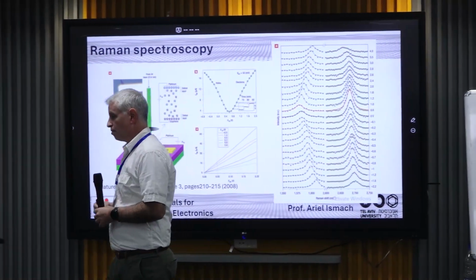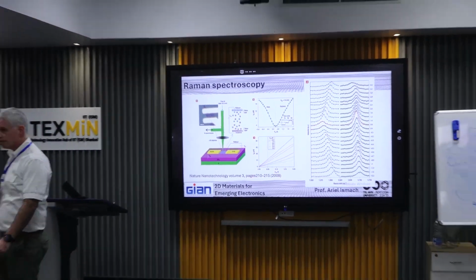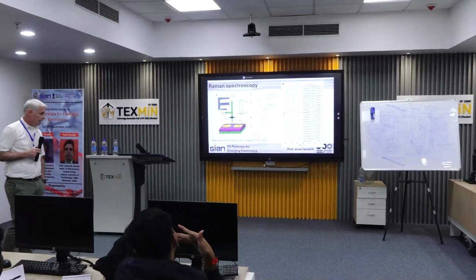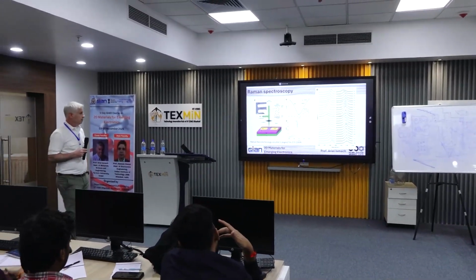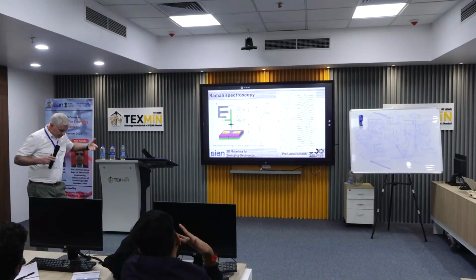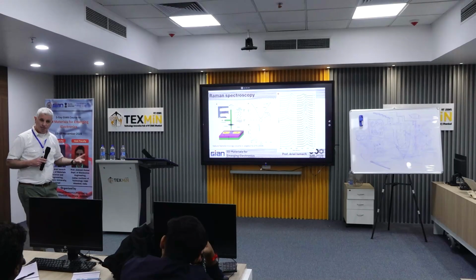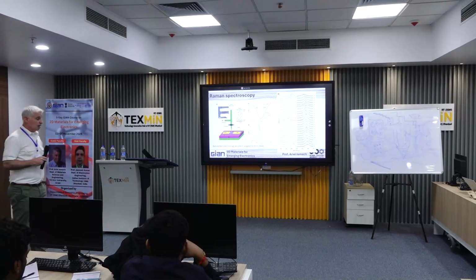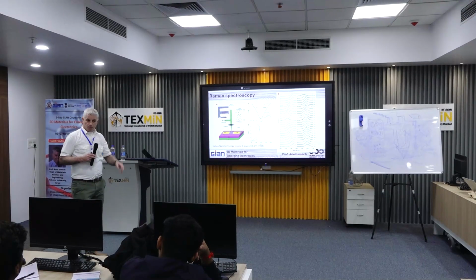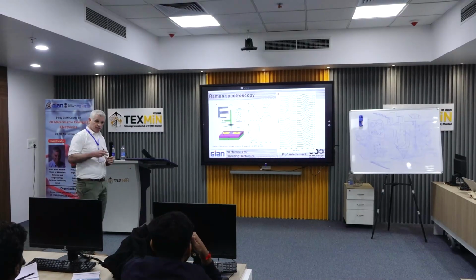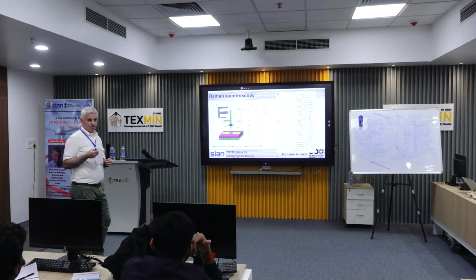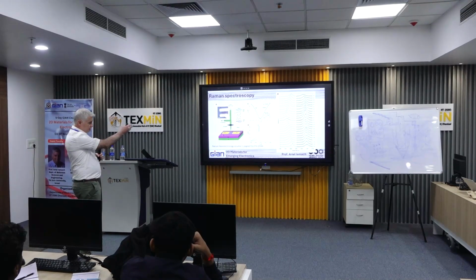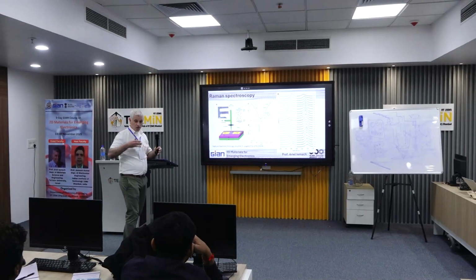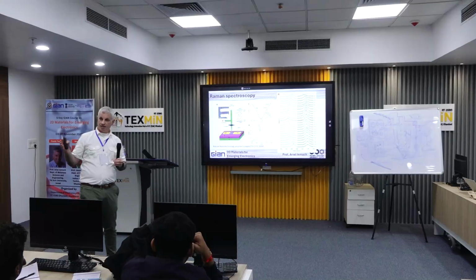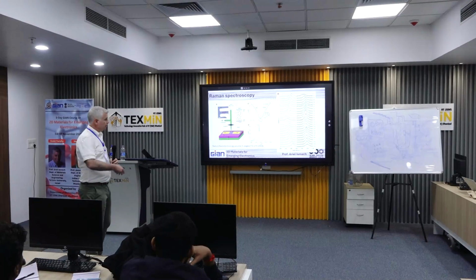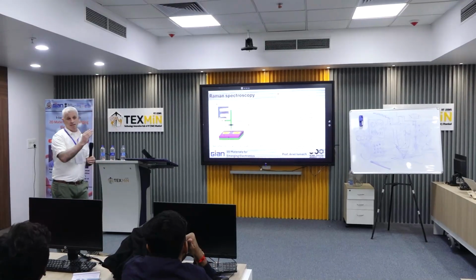So it can also be used to monitor changes in another field that is very useful. I mentioned the intercalation, right? Intercalating materials, compounds, molecules, atoms in between graphite plates is very interesting. And what is one of the ways to check that you have a good intercalation by Raman? One of the triggers for intercalation is charge transfer, and charge transfer is very sensitive to the G mode. So you can estimate the quality of the intercalation, how much of the intercalant you have in, by the G mode position, basically the shift.